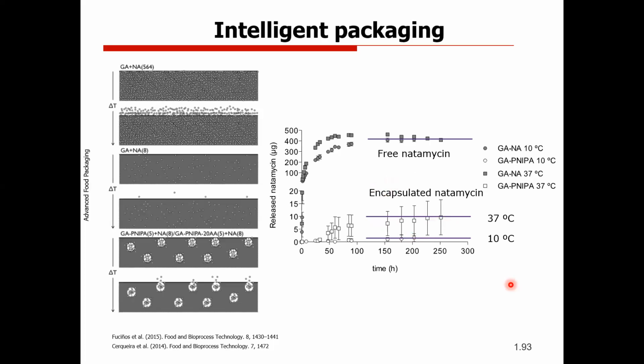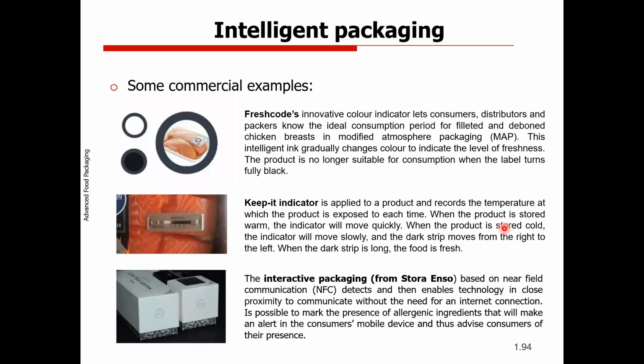Only to give you a detail here, you can see that for encapsulated, the values are lower than the free because the loading capacity is lower, and we believe that we don't need to use such a large amount. So the free natamycin incorporated is higher than encapsulated. So here we are at the maximum value. At 10 degrees, when encapsulated, we don't have the release of the compounds. And this is the kind of system that we are able to develop using intelligent materials, but with active properties.